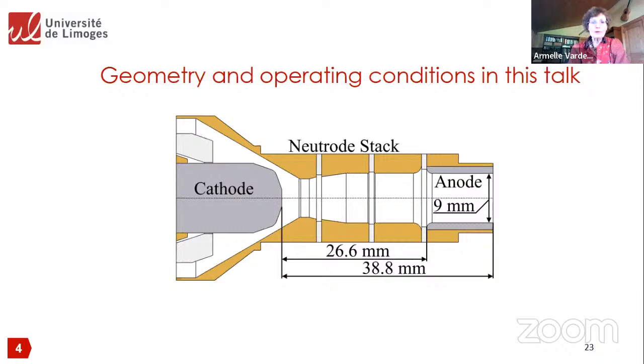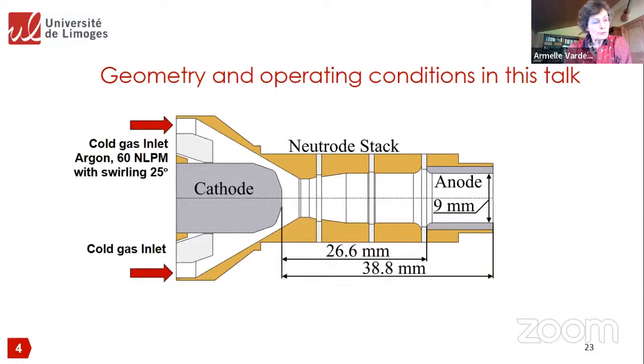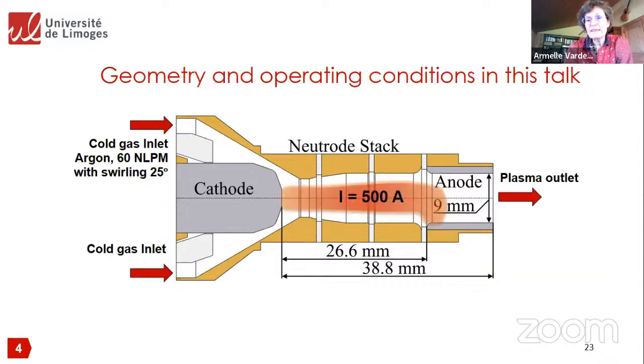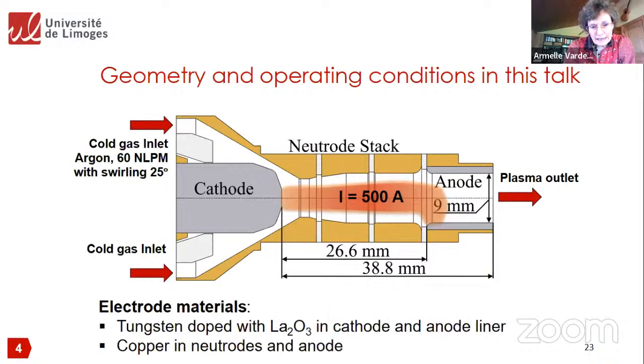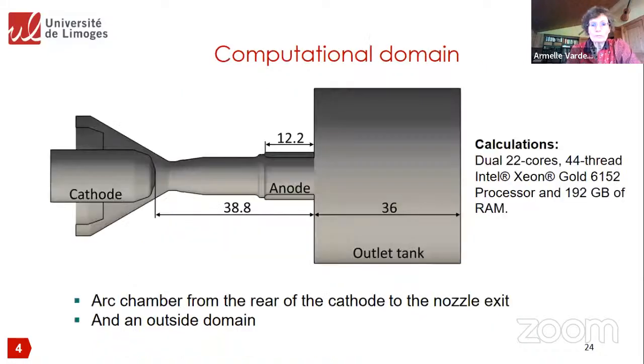So today I will just use one set of operating conditions. I will use pure argon, 60 liters per minute of argon, which is injected with an angle of 25 degrees. The arc current is 500 amperes, and the anode nozzle diameter is 9 millimeters. In the model, we have implemented the actual materials, that is, tungsten doped with lanthana, and we are using copper in the cathode and anode parts.